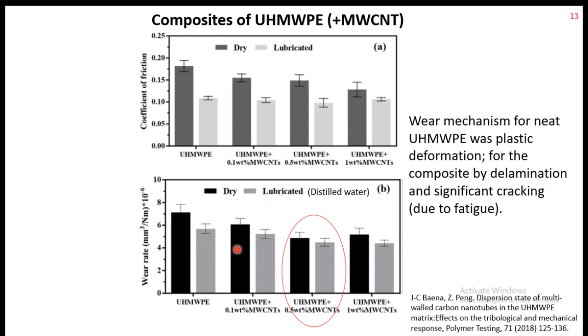So here we see that adding Multiwall CNT has reduced both friction and wear, at least in this research. It was found that the wear mechanism for pure UHMWPE was plastic deformation, and for the composites it failed by delamination and significant cracking. So here we can understand that by adding a filler like CNT, the material became a little bit brittle and cracking initiated.